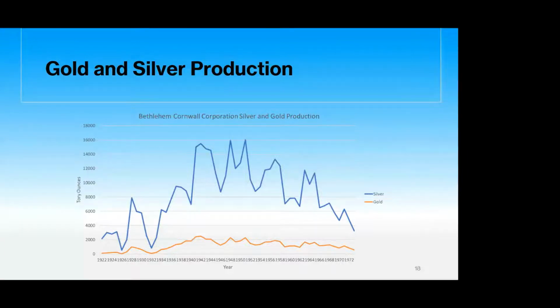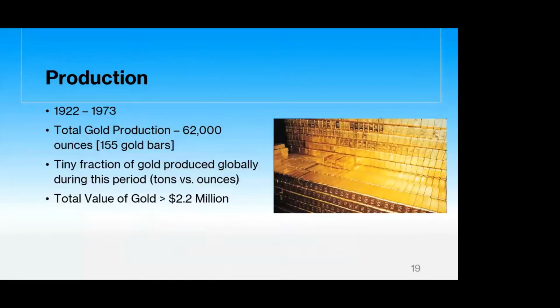These variations were primarily driven by changes in the amount of iron ore produced, concentrations of copper in the ore, and the recovery levels, or so-called practice, achieved by the flotation plant in the concentrator. So based on these records, I estimate that Cornwall produced over 62,000 troy ounces of gold.